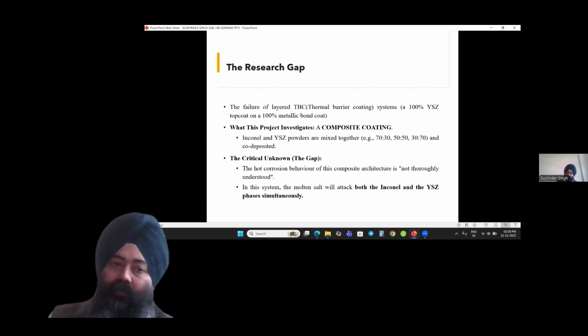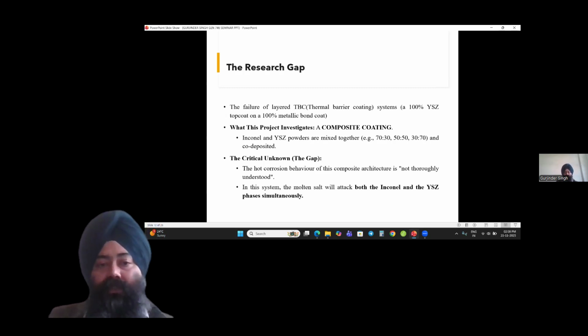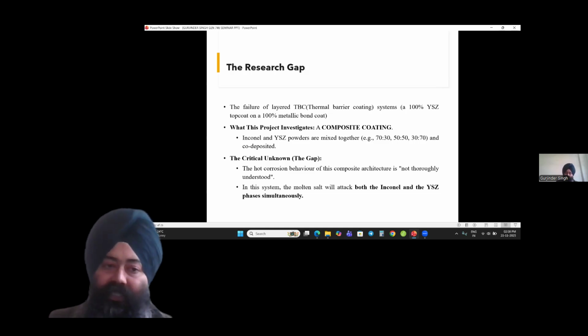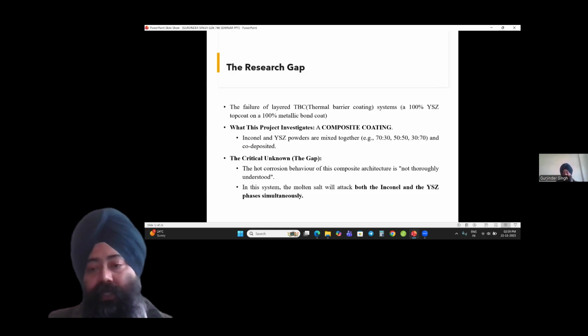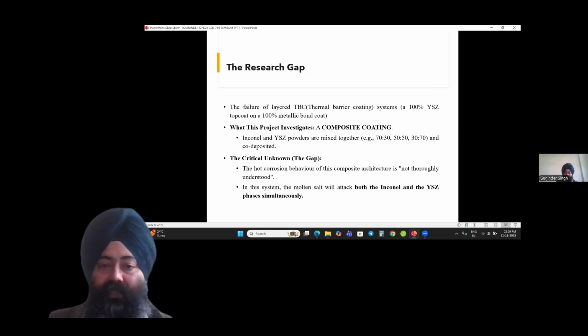So our research gap shows if we use only a thermal barrier coating with 100% YSZ or a 100% metallic bond coat. And what is unknown? What is the gap? The hot corrosion behavior of this composite architecture is not thoroughly understood. In this system, molten salt will attack both the Inconel and YSZ phases simultaneously.